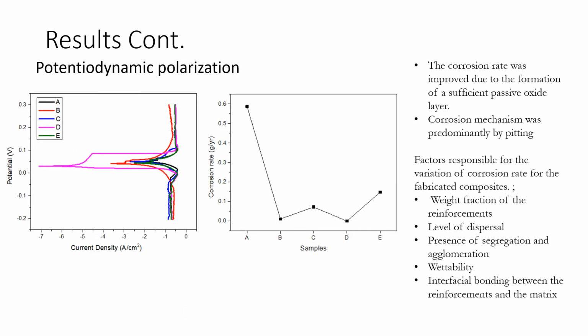For the corrosion resistance experiment, the investigation showed that the improvement in the corrosion resistance of the reinforced samples was due to the formation of a sufficient passive oxide layer. It was also noted that upon further exposure of the samples to the corrosion mechanism, the passive oxide layer breaks down, and after that, corrosion mechanisms initiate. The major corrosion mechanism identified in this study was localized pitting.